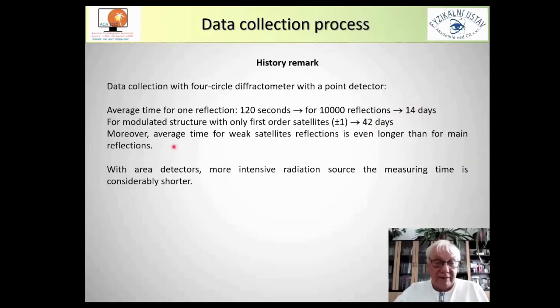But the average time for weak satellite reflections is usually much longer, and this means that these 42 days are even longer. Now with area detectors, making data collection of a modulated structure is generally not very different from data collection of a regular non-modulated crystal.